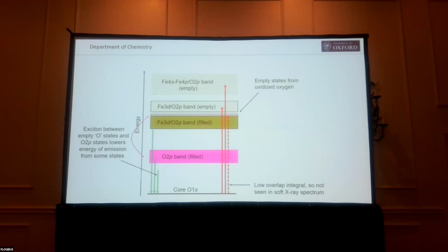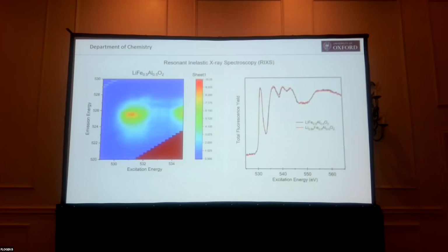And so what that means is when electrons drop down out of these bands, we're going to see an emission from an electron that sits in this band, which actually releases less energy than we expect from an interaction with these elements. So if we could energy resolve the emitted radiation, rather than measuring the total fluorescence here, we should be able to see it. And so what you can do is bring in resonant inelastic X-ray scattering, and that's what I'm doing here.